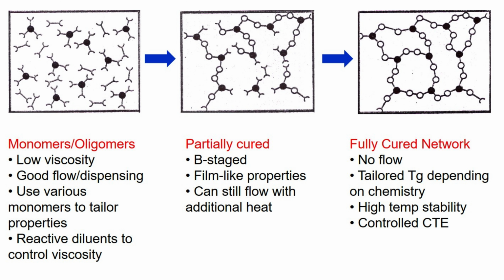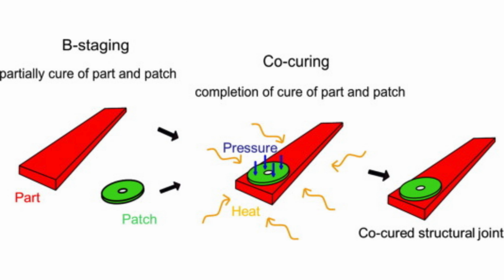B-staged resin. Many epoxy adhesives are capable of being B-staged. A B-staged resin is one in which a limited reaction between the resin and hardener has taken place so that the product is in a semi-cured but solid state. In the B-stage state, the polymeric adhesive is still fusible and soluble. On additional heat curing, the adhesive will progress from the B stage to a completely cured state. This will usually be accompanied by moderate flow.